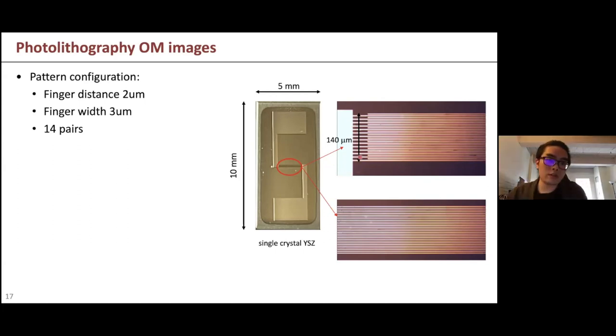This pattern is not very easy to make because it has a very high aspect ratio. Not only is the smallest feature size close to 1 micron, which I believe is the limit of the MLA in TRL and nano, but also I cannot risk any kind of deviation along this long finger. So you can imagine this has a 2 micron width, but it has around 3 millimeter length. So I have to make sure that it is 2 micron in width over all this distance. Otherwise, as long as it becomes a little bit fatter in the middle, or a little bit thinner, then the finger basically just breaks. All of my devices will just not work because they will either short or just break. So this took me some time, like weeks, to figure out. And I'm glad that it works now. The reproducibility of the recipe is very high, almost 100% now.